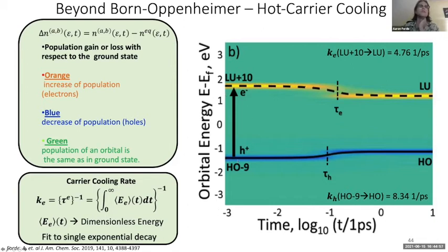And we can see that after the photoexcitation, the charges cool to the HOMO and LUMO states on a sub-picosecond time scale. And the interesting thing, if this image had higher resolution, is that there's kind of a smear as the charge cools down to the LUMO state. And so to investigate that feature more, I plot this dotted curve, which is the change in energy over time, to a normalized scale on the next slide.